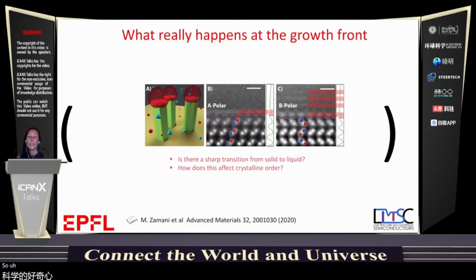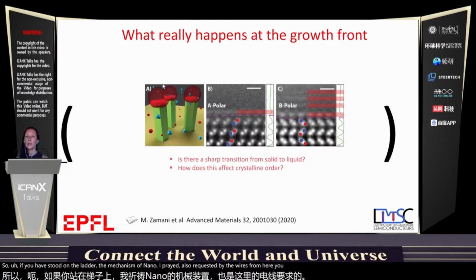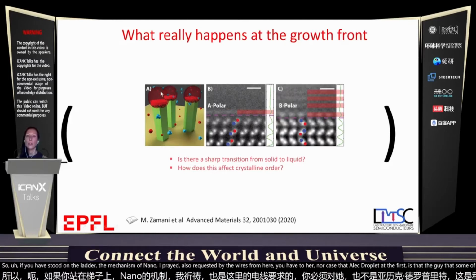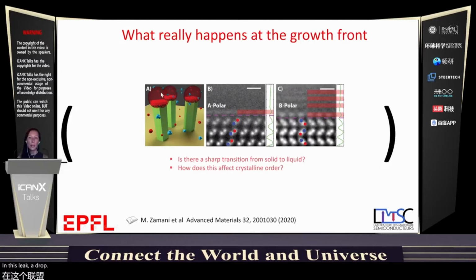So if you have here on the left the mechanism of nanowire growth, you have the nanowires growing here, you have in our case the gallium droplet and the precursors that arrive, and some of them get dissolved in this liquid droplet, and they precipitate and combine with the gallium to form gallium arsenide.